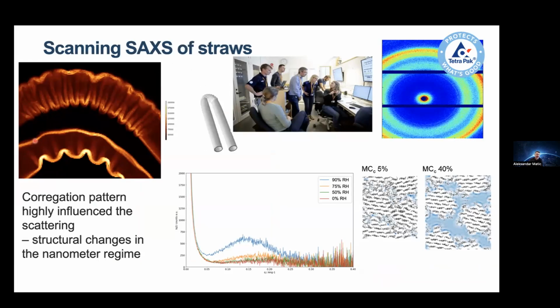You should disregard the bright parts on the surface, because this is just some edge effects, but instead look into the bulk here, for instance, of this straw. So this is a straw made out of a biopolymer, and we are zooming in on the part where we are bending. And you can see here there are two different designs, one with a very high frequency on the corrugated pattern, and one where there is much less.